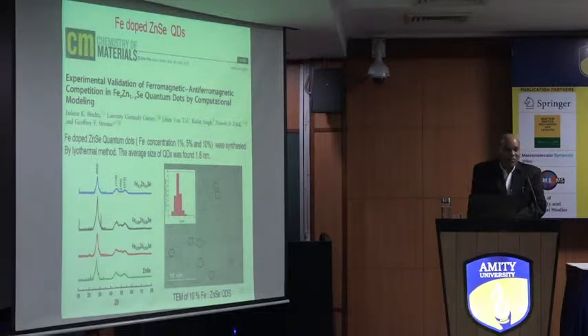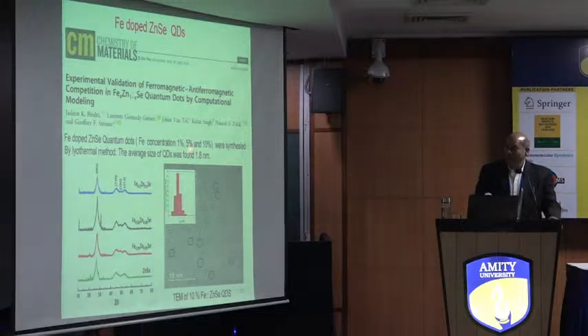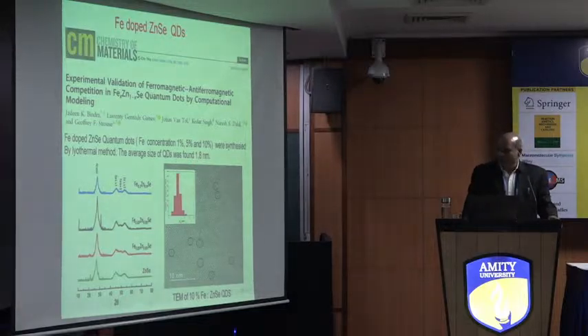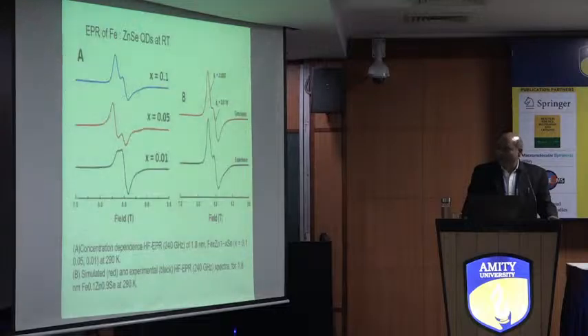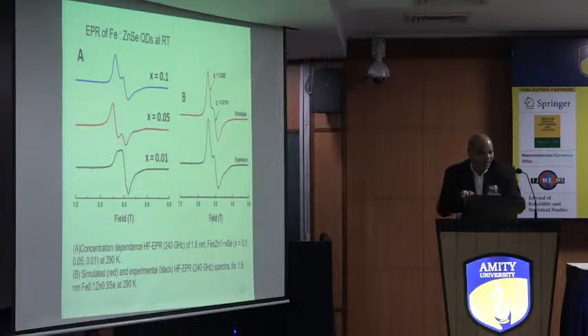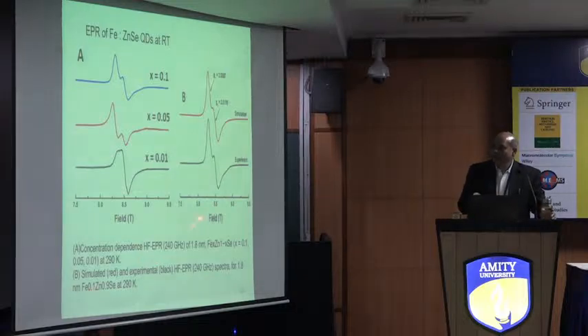Other work is on the iron doped ZnSe quantum dot. Here we prepared 1%, 5 and 10% iron doped ZnSe quantum dots. Here you can see the dot size is very, very small, 1.8 nanometers. And this is my work, the EPR at room temperature. Here we get iron 3 doped in this ZnSe quantum dot.